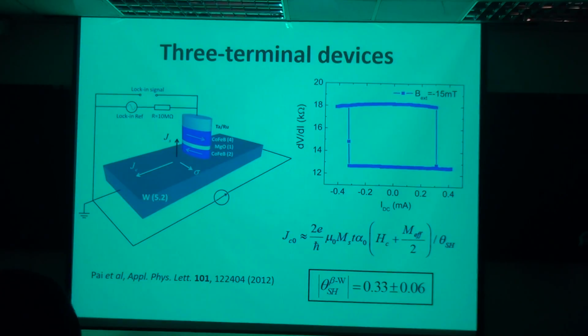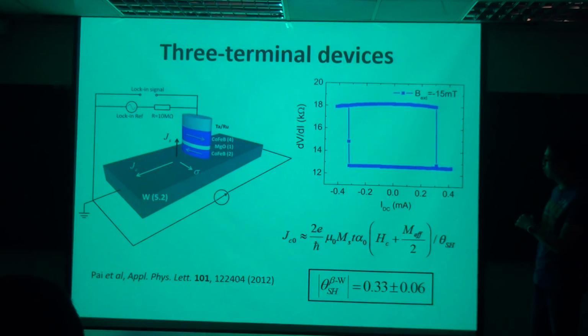And you'll see that the spin-Hall efficiency for tungsten, or beta tungsten, is 33%. So it's even larger than beta tantalum. And even till today, I think beta tungsten is still the transition metal with the largest spin-Hall angle in terms of its magnitude.